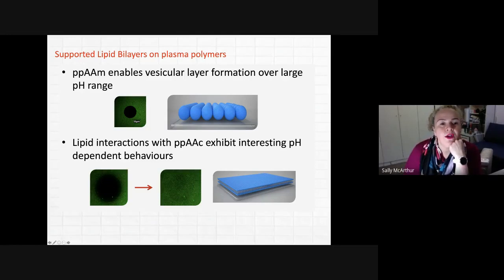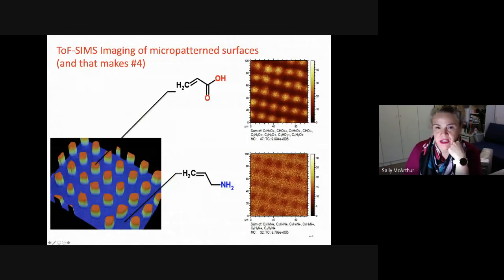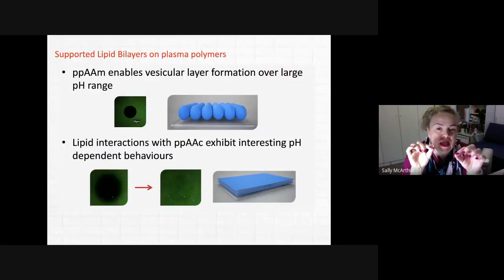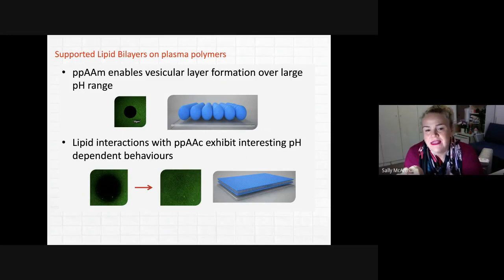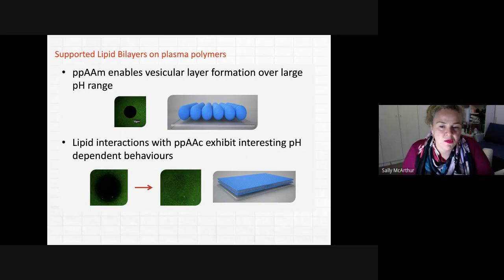So here we photobleach an area. In each of these lipids, my apologies, we've got some fluorescent tag. And if we photobleach an area of the surface, if the lipids are mobile, they'll actually be able to move through and recover the fluorescence in the area. But you can see here on the vesicle layer, it doesn't recover, telling us it's not mobile. But here on the acrylic acid surface, we photobleach, and after 5 minutes, the lipids are able to move around and we can recover. We can see a shadow of where we've photobleached, so it's not a perfect recovery, but lipid mobility is a really important characteristic if we want to create functional surfaces that replicate biology.